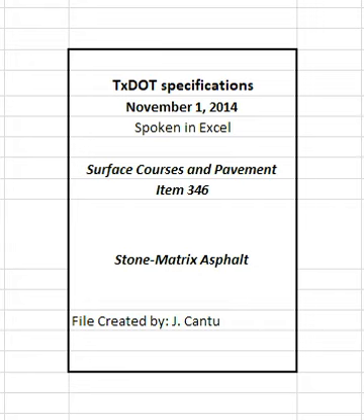4.9.3.3.1 In-place air voids. The engineer will measure in-place air voids in accordance with Tex-207-F and Tex-227-F. Before drying to a constant weight, cores may be pre-dried using a CoreLok or similar vacuum device to remove excess moisture. The engineer will average the values obtained for all sublots in the production lot to determine the theoretical maximum specific gravity. The engineer will use the average air void content for in-place air voids.